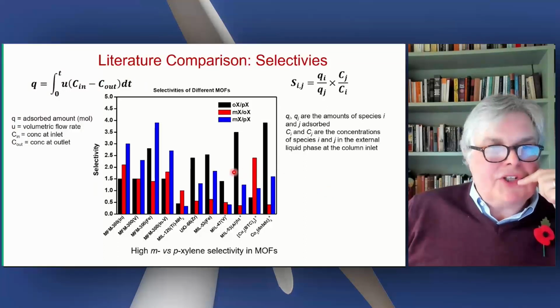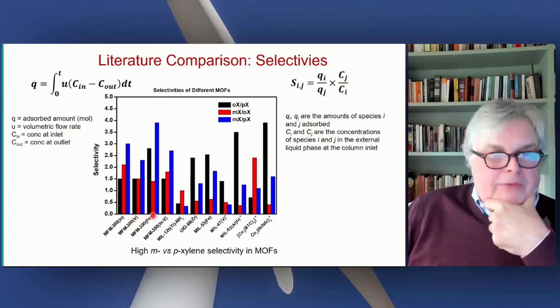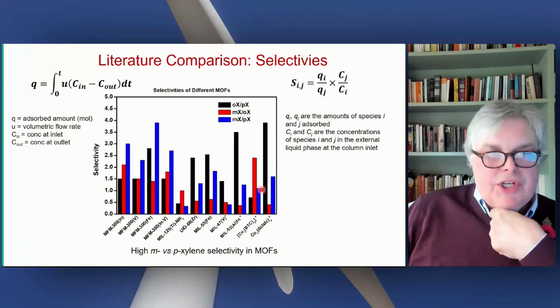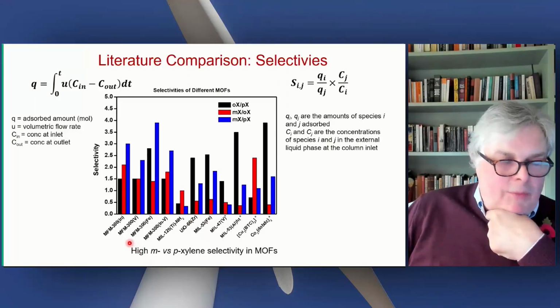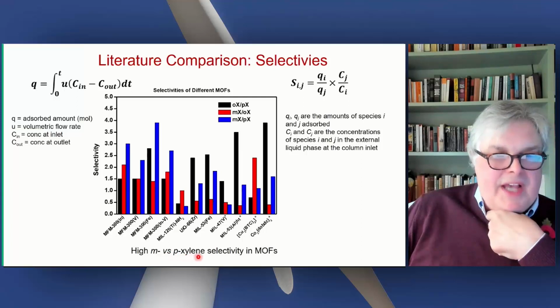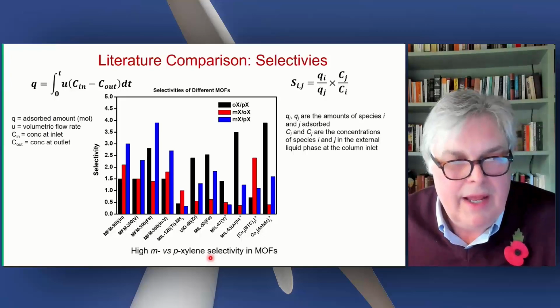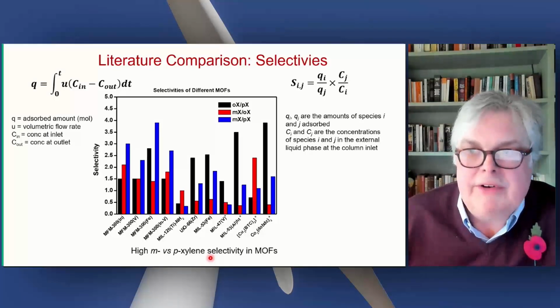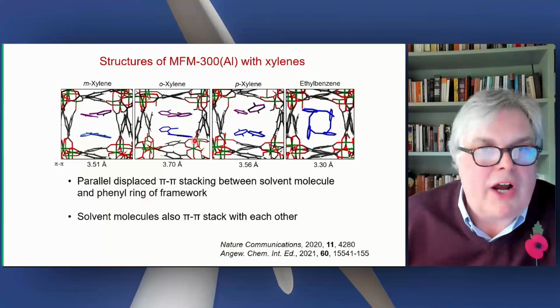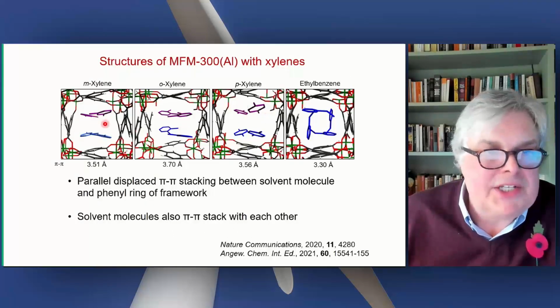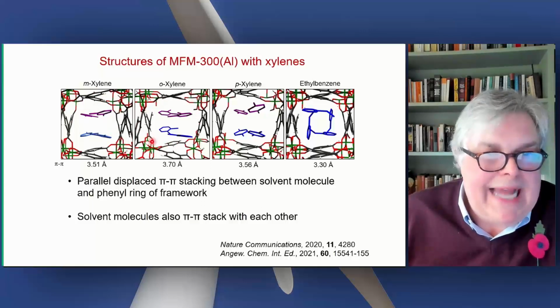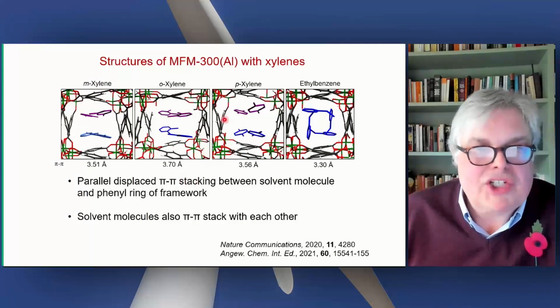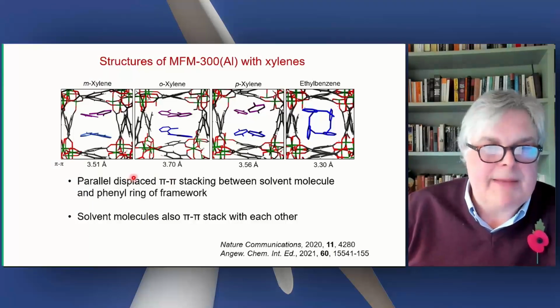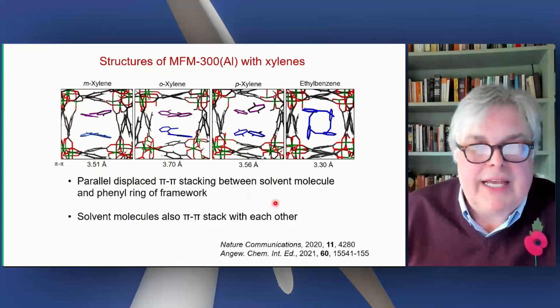Again, comparing this with literature, different MOFs will have different selectivities. I just wanted to show this in general form. What we observe is often meta versus paraxylene selectivity in our systems. That seems to be something that we observe in many of these materials. And we link that into the structures of these xylenes. And I just illustrate that we can get structures. We can analyze the various pi-pi stacking interactions and then relate that back to the observed separations, or the lack of separation as it is.